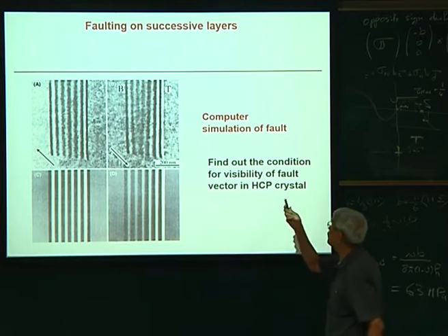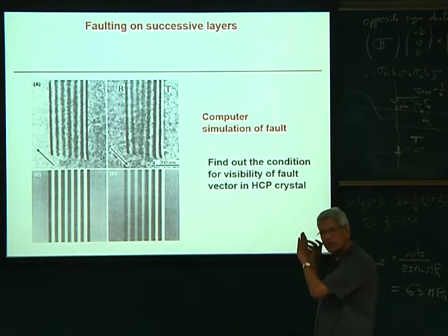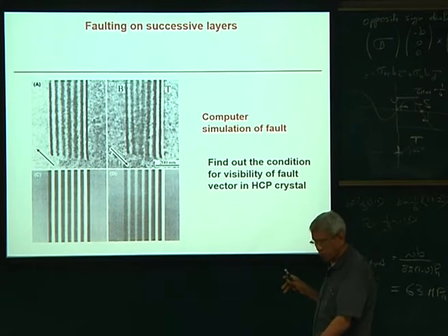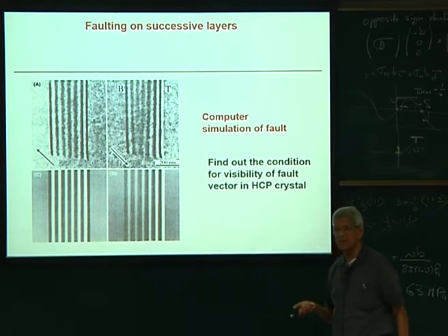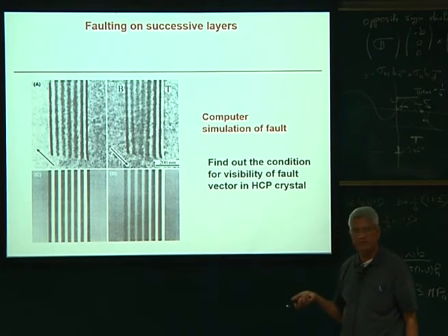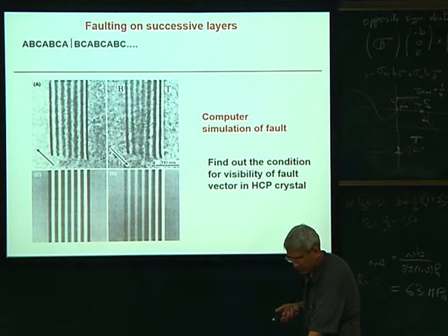This is one where, in some low symmetry alloy, the stacking faults have to be simulated to find out what the fault vectors are. This I had mentioned yesterday, what all information is required to do that. We require the g vector, the line direction, the foil normal which we should know, the extinction distance, xi g, and the thickness of the foil we should know.